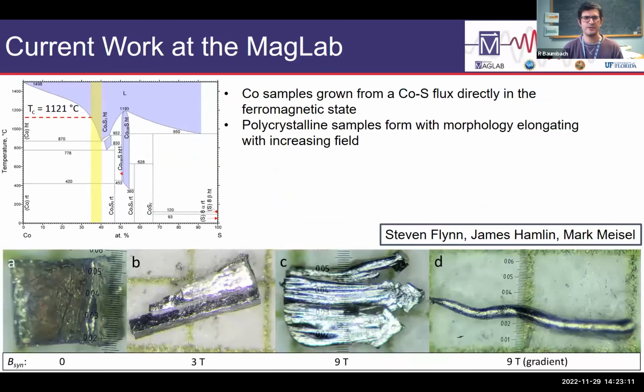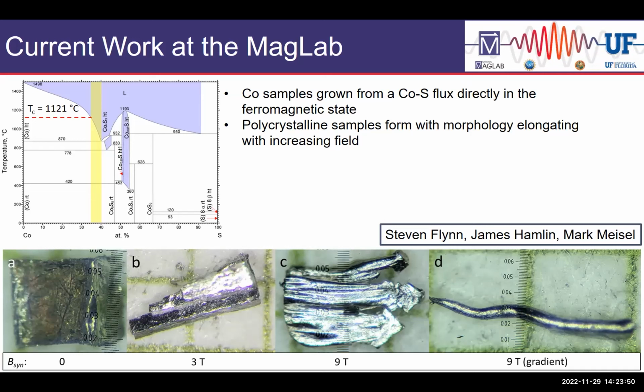All right, one of those early experiments is shown here. This is an interesting idea where if we consider the binary phase diagram that's shown in the upper left-hand corner for cobalt and sulfur, you can see that the melting line, which is illustrated by the separation between the white area and the purple area, if you go into the right concentration range, this melting temperature drops significantly. And in fact, it drops below the Curie temperature of cobalt. So now you have the opportunity to grow cobalt crystals within the ferromagnetically ordered state. What will this do? We don't actually know. But you can see that it has an impact.